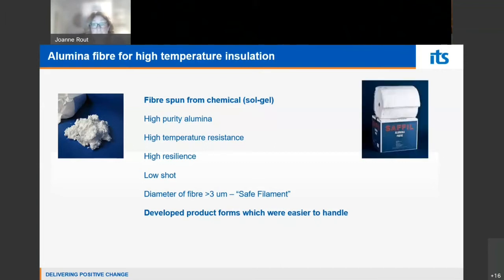It's used in insulation, and as it's spun, it forms a thick blanket. What we wanted was something a bit more compressed, that could be easily processed when people were using it in high temperature furnace insulation. With other fibers, you can just press needles through, and the fibers are drawn through the blanket and compress it to low thickness. That doesn't work with Saffil. What we had to do is put an organic polymer layer on the top and do stitching through, and the polymer fibers formed allowed the product to be compressed, and then when it's used in the furnace, the polymer burns off.